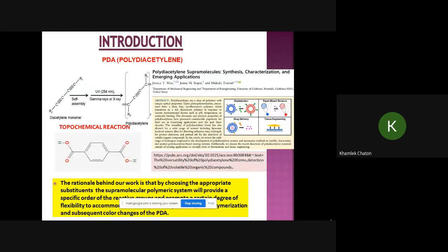It is basically a polymer made out of diacetylene by topochemical reaction. The suitable condition for polymerization is that the chain needs to be at a 45-degree angle and the distance between the diacetylene chains should be 5 angstrom. So they self-assemble and form the polymer. PDA is an amazing optical polymer. After polymerization, it forms a deep blue color, which is non-fluorescent. But under a certain condition, it forms a fluorescent red color. That condition is exposure to heat, that is thermochromism.